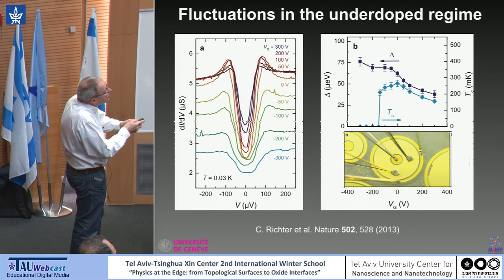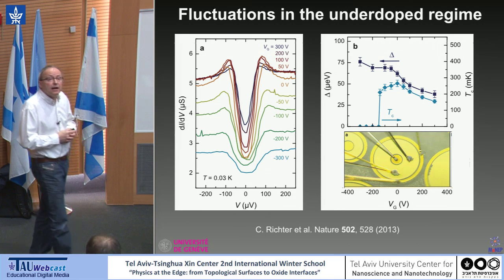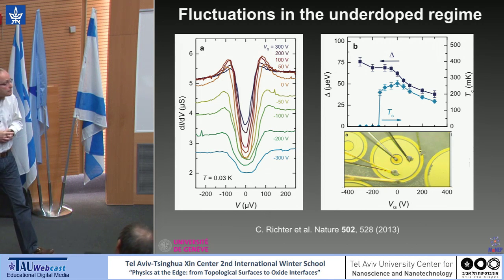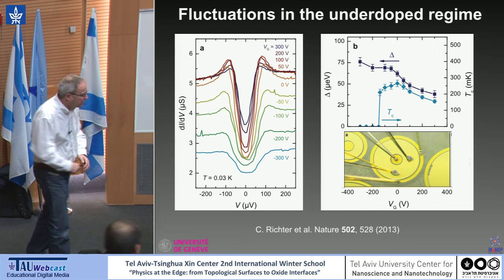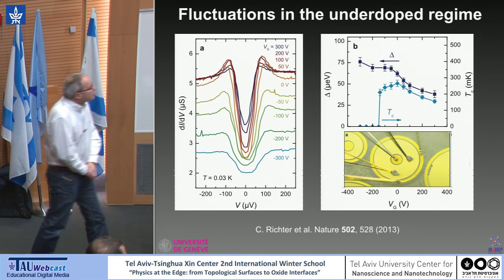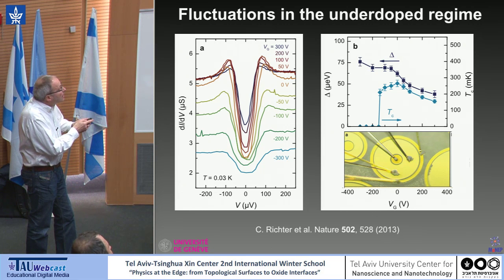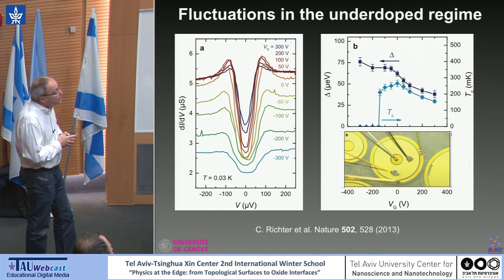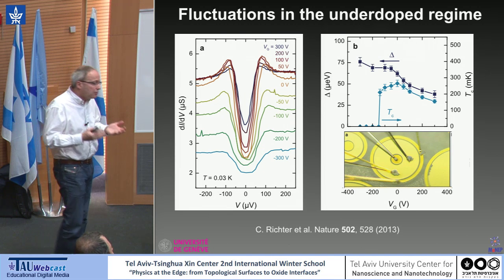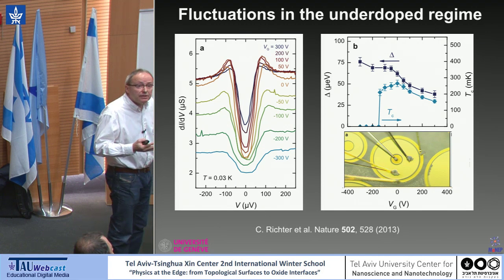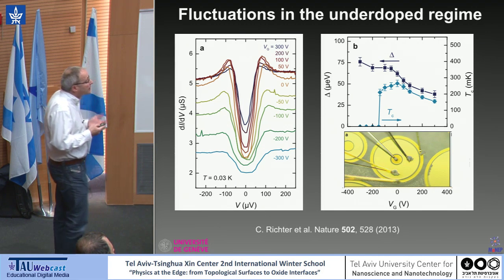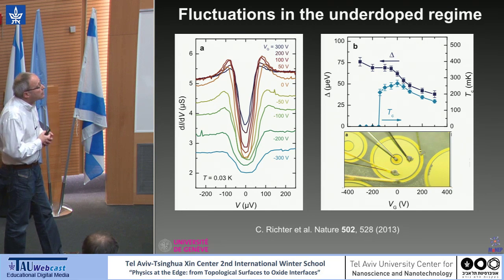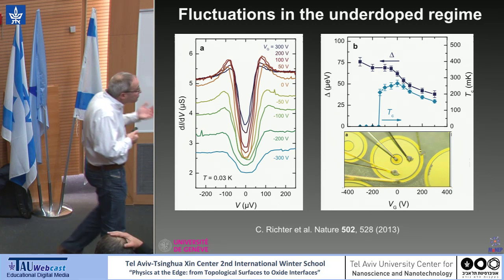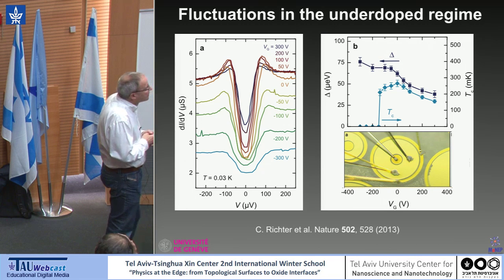So the gap is increasing as TC is increasing, everything is fine. But you see here now the very unusual behavior which is observed. The gap continues to increase as TC is going to 0. So the gap is not following TC. Yes, oh, I should speed up. Okay, so this is very unusual, and their explanation is that there could be a fluctuating superconducting region in this area, something which goes maybe in line with the fact that we have a lot of fluctuations on this side of the phase diagram.